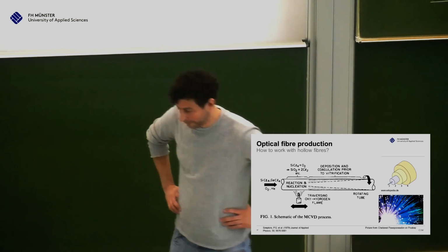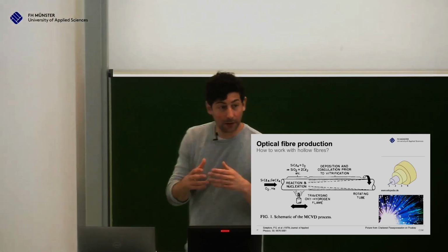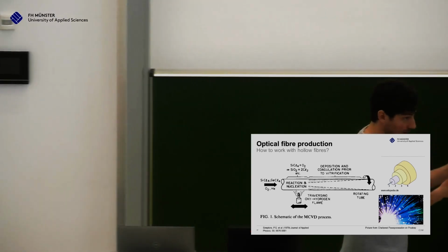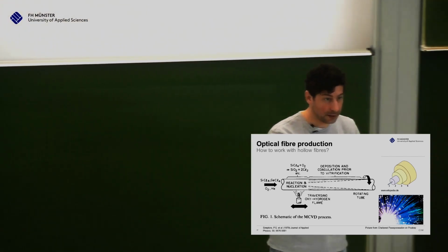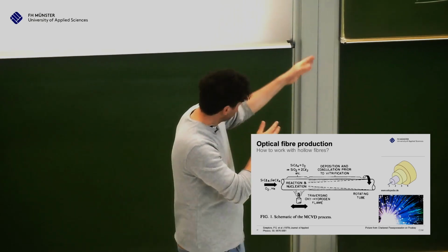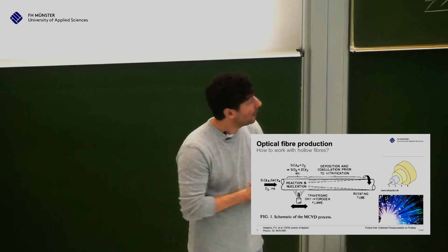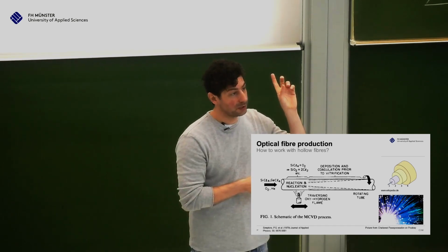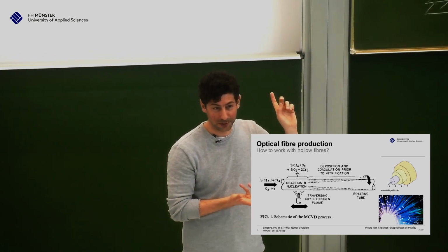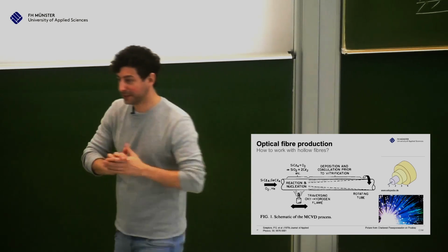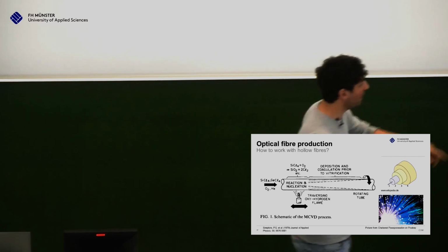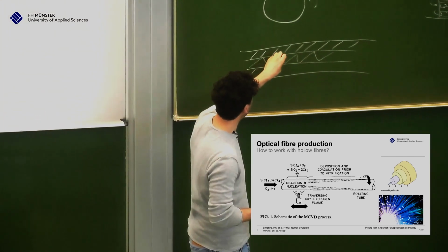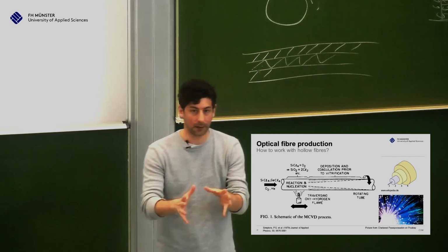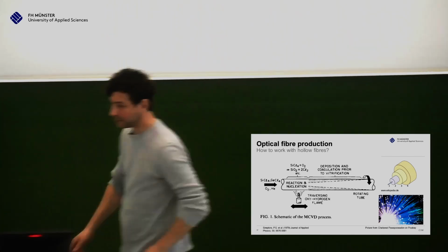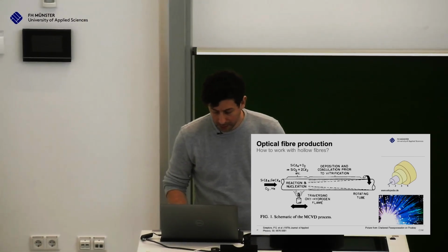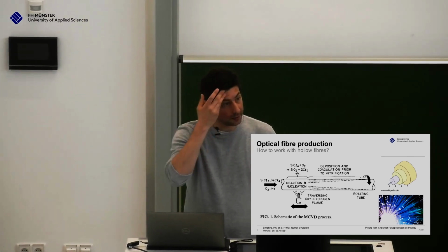So we have a gaseous precursor. It's silicon tetrachloride and oxygen, and they both react to SiO2 and some other things. And SiO2 is the glass we want to have. And we had a process before. You also see it here in abbreviated. Which process do we use? CVD. So it's a CVD process, but it's called MCVD, modified CVD, because it happens inside. And what you create is you not directly grow this structure, you grow nanoparticles. Okay, so here in the middle, and basically I show it here on this image, because there's a very nice Wikipedia article. The Wikipedia article explained it quite well.